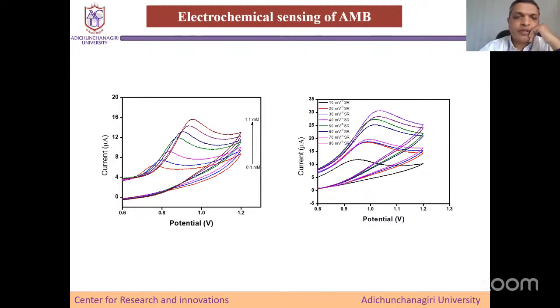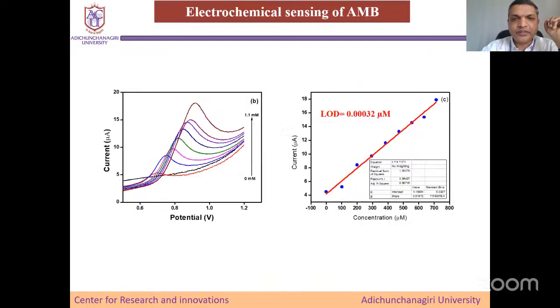Current versus potential by varying the scan rate, with concentration from 0.1 millimolar to 1.1 millimolar. As the concentration changes, the potential also changes. That indicates the composite is sensing amlodipine besylate. And when we plot current versus concentration, we get a straight line, and the limit of detection is 0.00032 micromolar. Using the nanocomposite, we can detect this particular medicine, amlodipine besylate, even at a 0.00032 concentration.